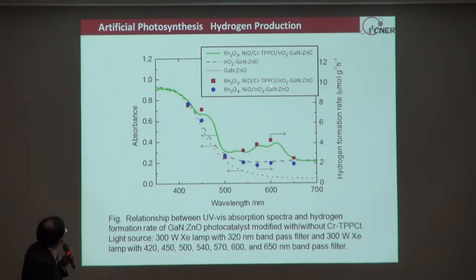And then recently we obtained another interesting result here. In this experiment, we used a 320 nanometer bandpass filter for the irradiation. And then we measured the formation of hydrogen as a function of the second light wavelengths. And as you can see here, if the excitation is in the gallium nitride doped with zinc oxide, then we can use light up to 600 nanometers, or sometimes much higher than 600 nanometers. And the dependency of the formation rate on the wavelengths is quite similar to that of the absorption spectrum of the catalyst. And this suggests that the double excitation is very successfully achieved.